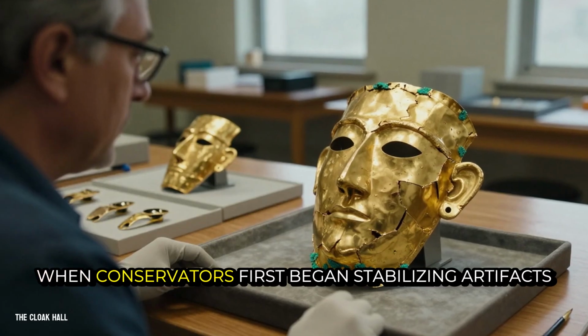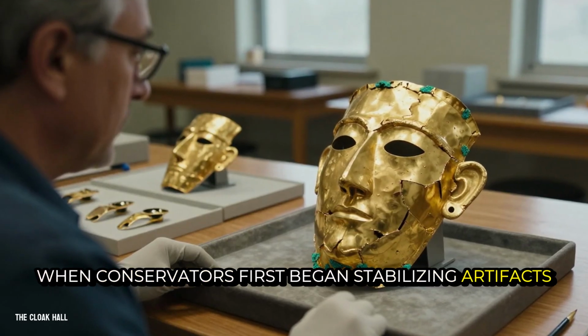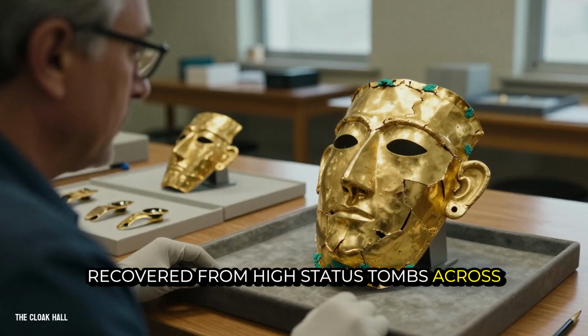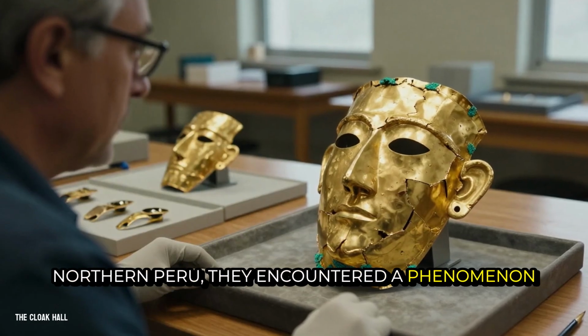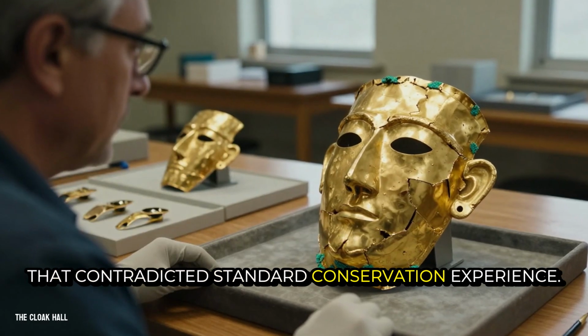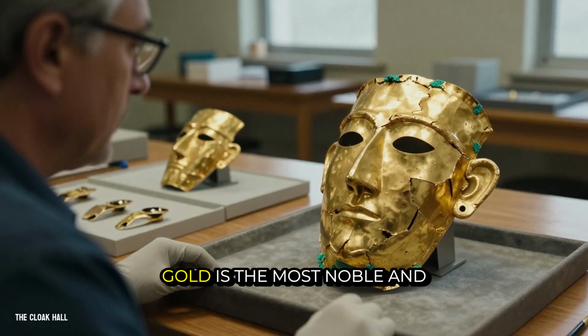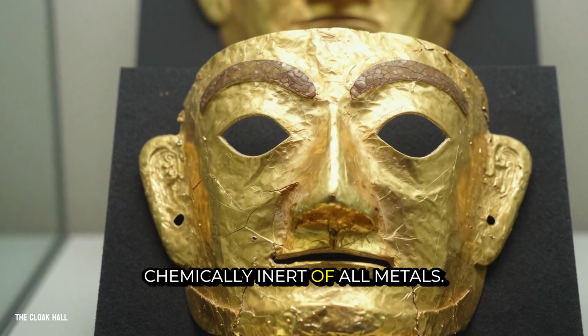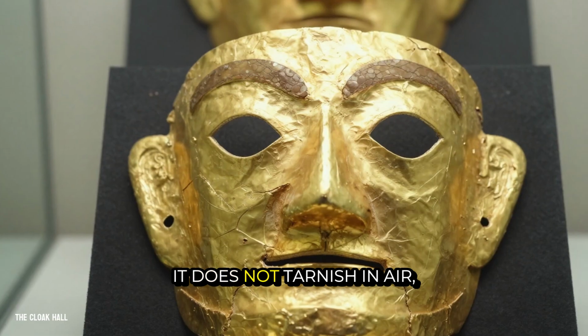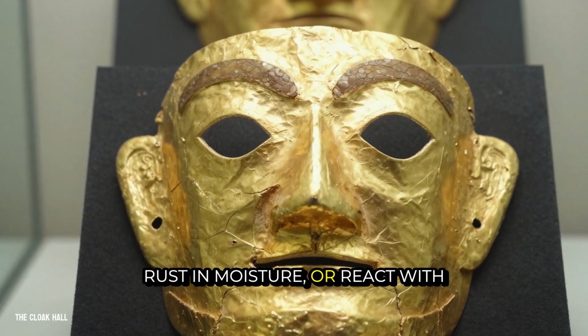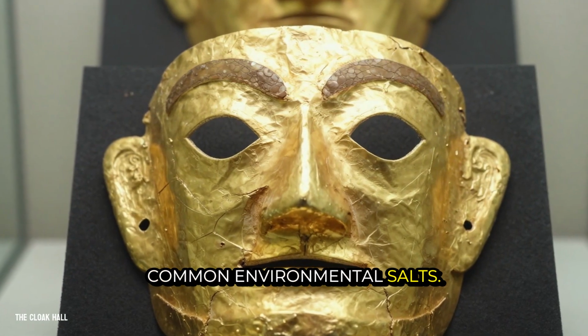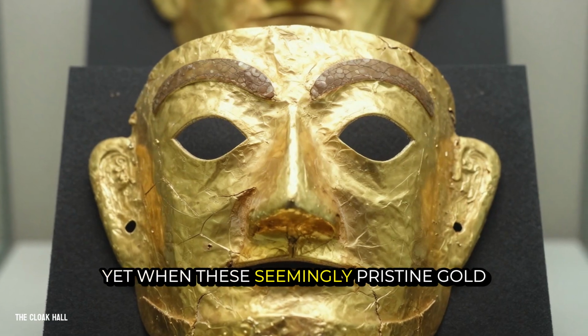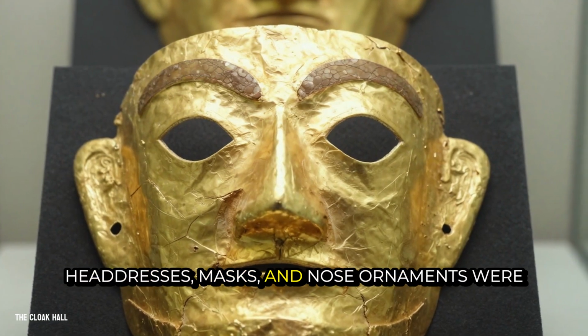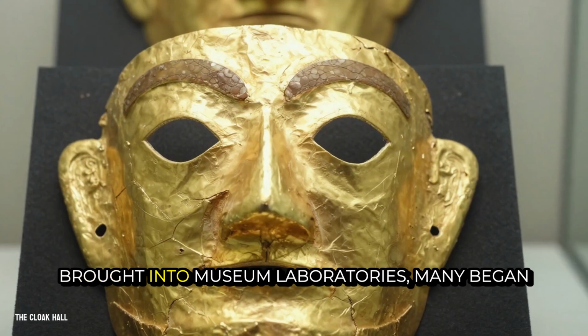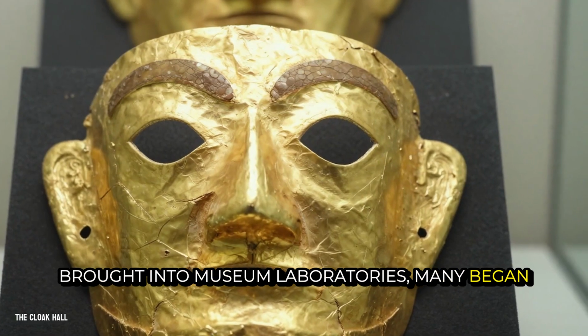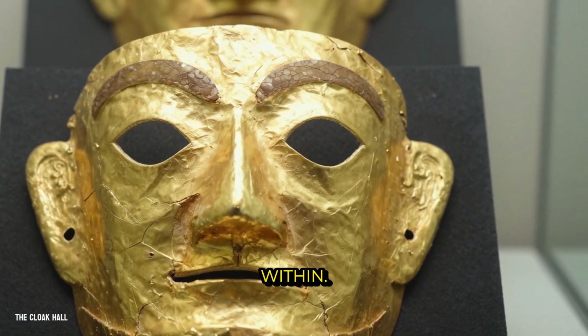When conservators first began stabilizing artifacts recovered from high-status tombs across northern Peru, they encountered a phenomenon that contradicted standard conservation experience. Gold is the most noble and chemically inert of all metals. It does not tarnish in air, rust in moisture, or react with common environmental salts. Yet when these seemingly pristine gold headdresses, masks, and nose ornaments were brought into museum laboratories, many began to swell, warp, and crack from within.